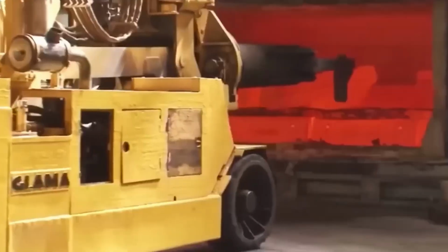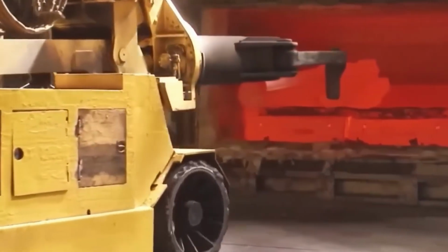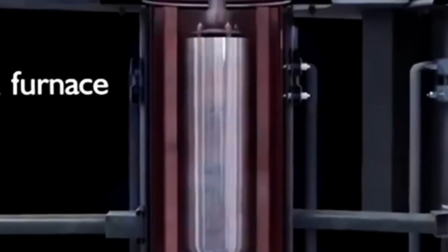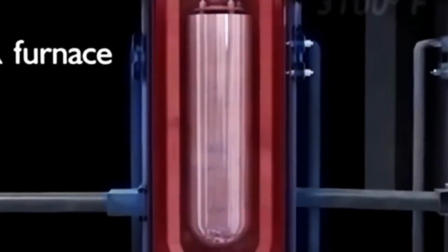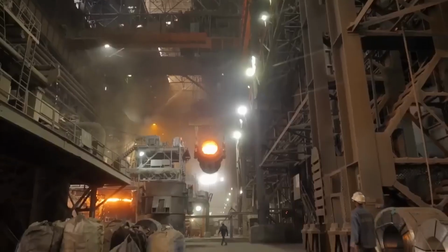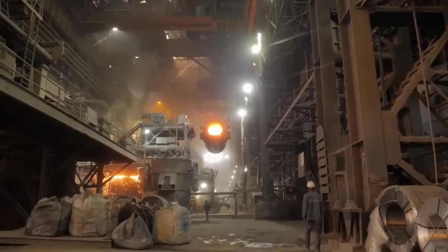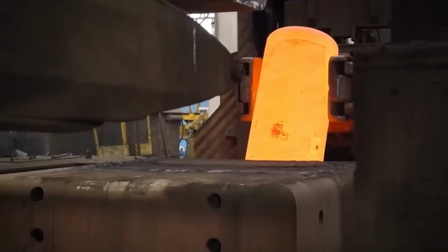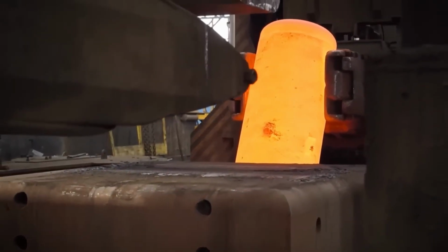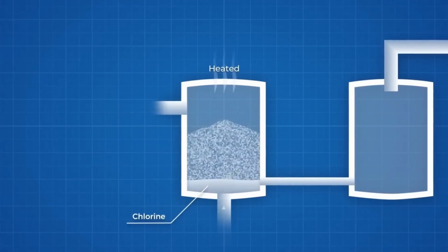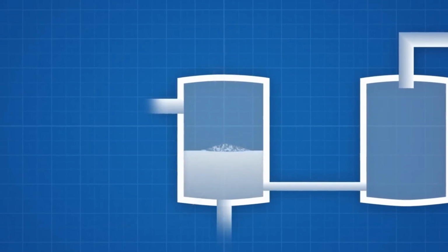To convert it into usable material, it must be separated from the trapped salts. This separation is carried out by vacuum distillation or leaching, depending on the process. In vacuum distillation, the reactor is heated under low pressure to evaporate the magnesium and magnesium chloride, which are recovered and can be recycled. This stage is energy and time-consuming.